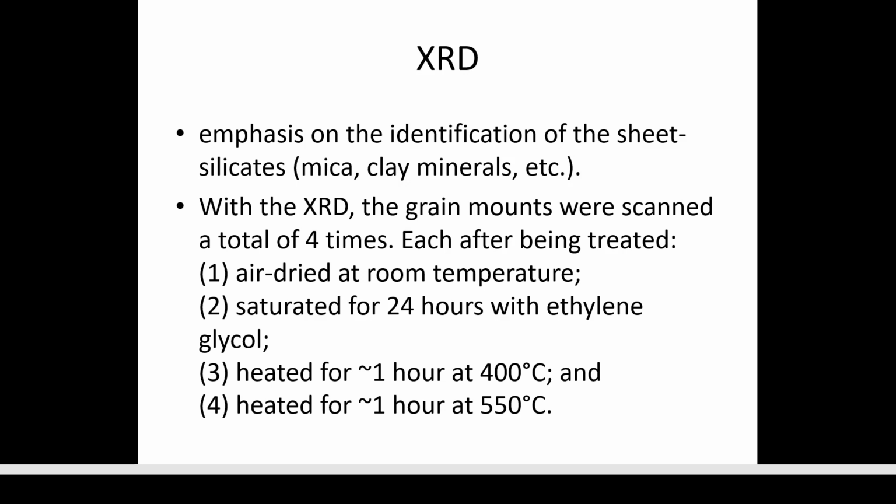With the XRD, the grain mounts were scanned a total of 4 times. This was following along with the USGS sample method of how to identify clay minerals. Firstly, the first treatment is air dried at room temperature. Therefore, nothing is done to the XRD slide.